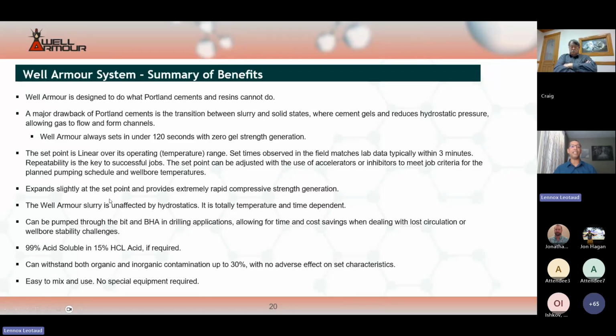The Well Armour expands at the set point and it builds compressive strength rapidly after setting. It is totally temperature and time dependent. It is unaffected by bottom hole pressure. Due to the micron size particulate nature of the slurry, you are able to pump it through a bit. You are able to pump it through narrow IDs. As shown earlier, it is acid soluble with 15% HCl. It can withstand contamination up to 30% and still achieve close to the design set time characteristics. And no special equipment is needed or required to mix and pump Well Armour.